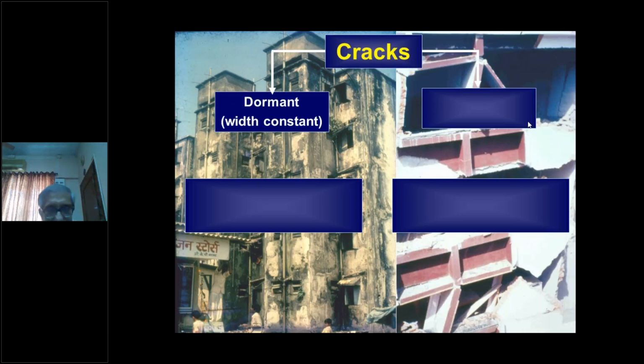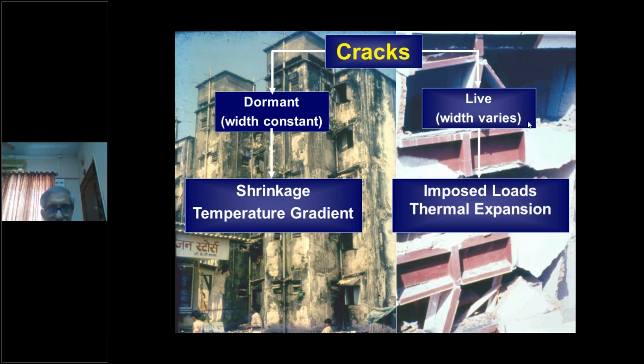Further, cracks can be classified in two ways: the dormant cracks and the live cracks. Dormant cracks are cracks where width will remain constant. For example, shrinkage, once it occurs, it cracks the concrete and the crack remains almost the same. But the danger is it will allow water, moisture, chemicals, and cause a problem of durability. Temperature gradient cracks also are dormant cracks. But the live cracks are due to imposed load and thermal expansion and contraction. An imposed load could be due to earthquake, or due to addition, alteration, or due to addition itself of a heavier type, and therefore these cracks are live cracks and dangerous.